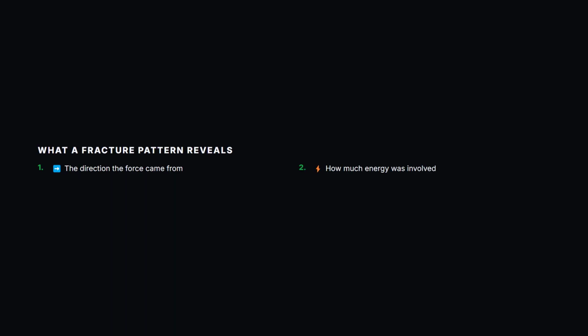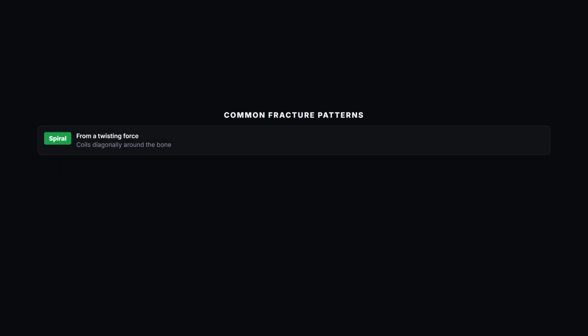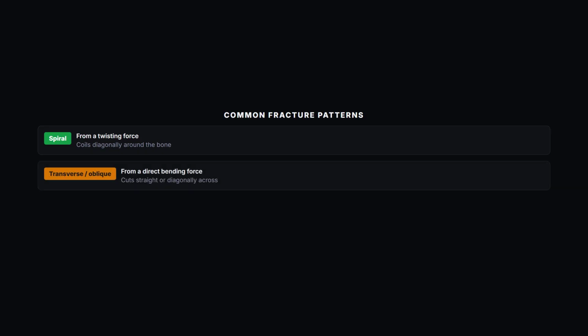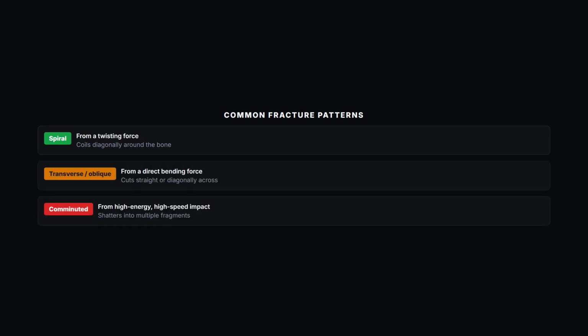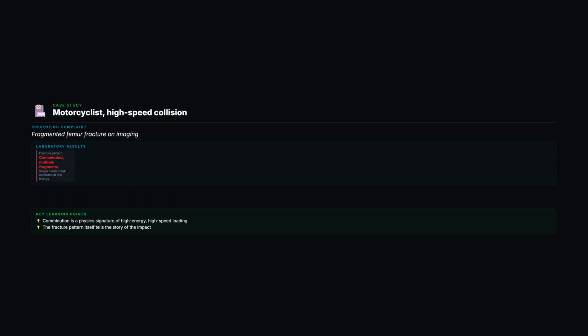A twisting force tends to produce a spiral fracture, coiling around the bone like a corkscrew. A direct bending force tends to produce a transverse or oblique fracture, cutting straight or diagonally across. And a high-energy, high-speed impact tends to produce a comminuted fracture, shattering the bone into multiple fragments rather than one clean break. A motorcyclist involved in a high-speed collision presents with a badly fragmented femur fracture on imaging, multiple bone pieces rather than a clean break.